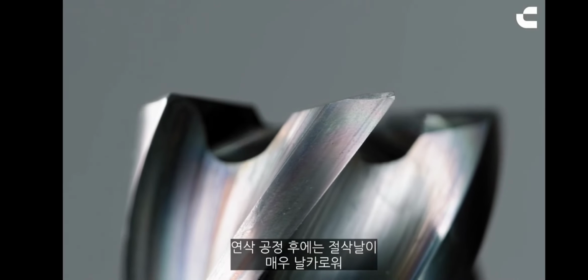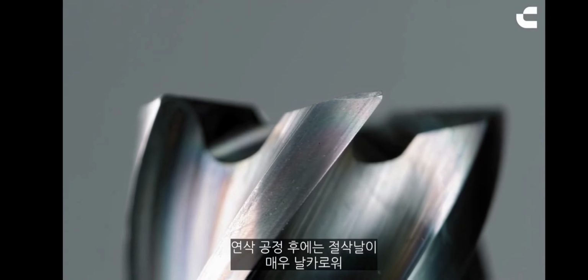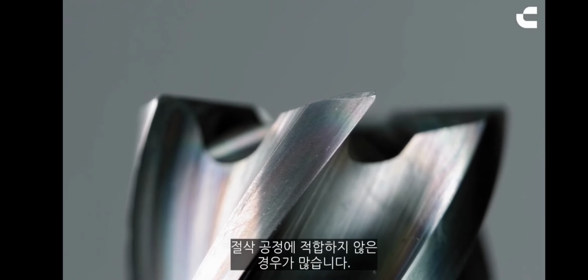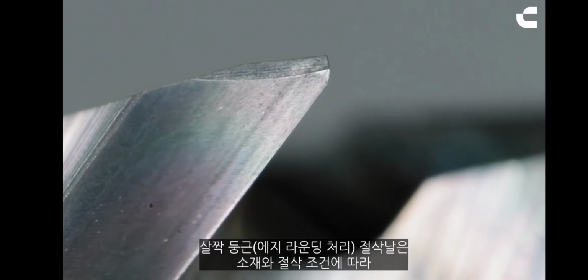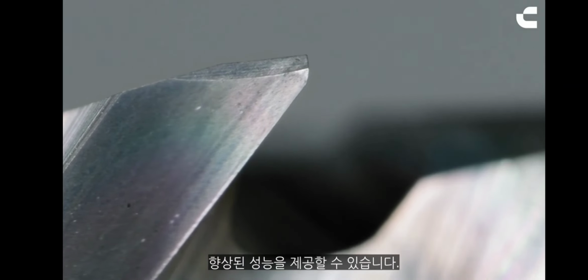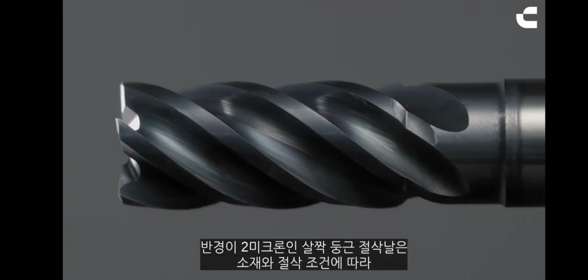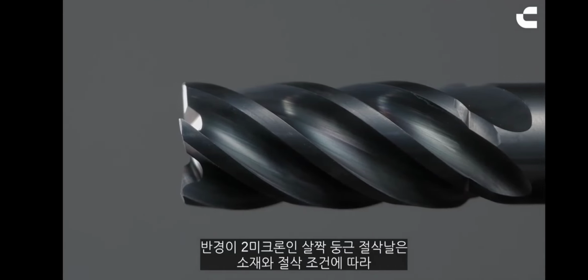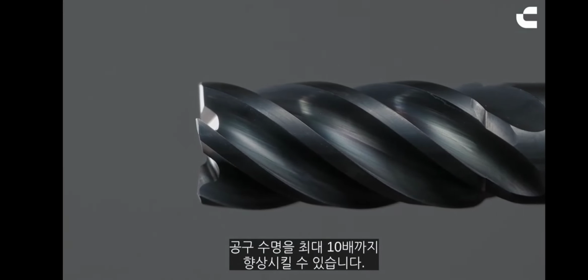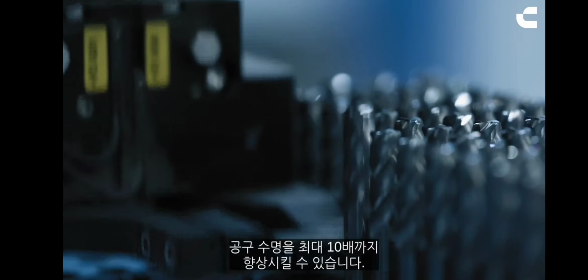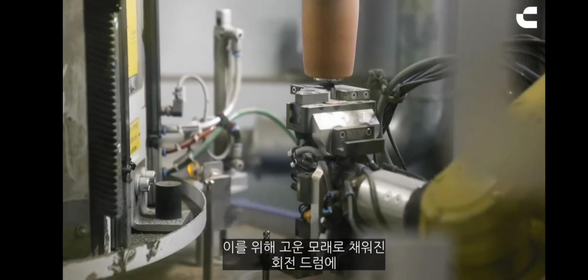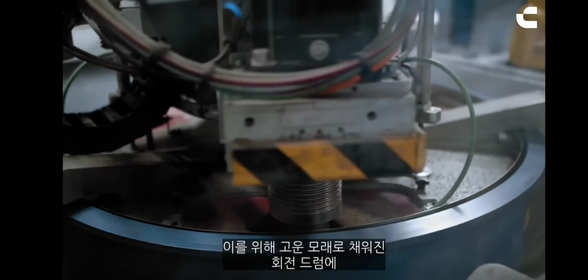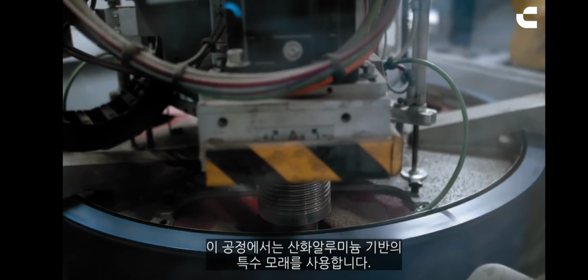After the grinding process, the cutting edge is extremely sharp, which is often not optimal for the cutting process. A slightly rounded edge can offer improved performance based on the material and cutting conditions. A rounded edge with a radius of 2 microns can improve the tool life by up to 10 times, based on the material and cutting conditions. This is achieved by dipping the tool into a rotating drum filled with fine-grained sand. For this process we use a special sand which has a base of aluminum oxide.